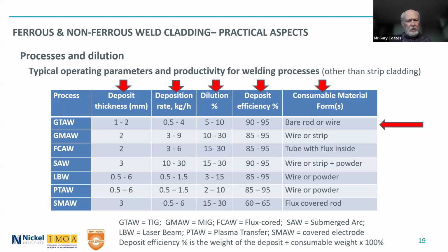So if we take gas tungsten arc welding or TIG welding, you don't get a really thick deposit. You don't get a high deposition rate. It's relatively slow, as we all know, but you do get low dilution, or at least you can get low dilution. And that's one of the factors to consider, that if you can do it in 1 layer or 2 layers with low dilution, you can be more economical that way.